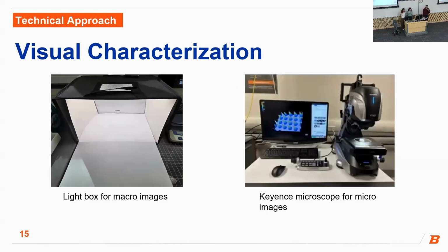EIS helped us to collect quantitative data, but to get a visual representation of our corrosion, each sample was macro and micro imaged pre and post immersion testing. The macro images were taken with a phone and a light box, while the micro images were taken with the Keyence optical microscope in the IMO. Imaging was used to locate where the corrosion occurred. Now that you know how we conducted our research, Lucy will present what we found.